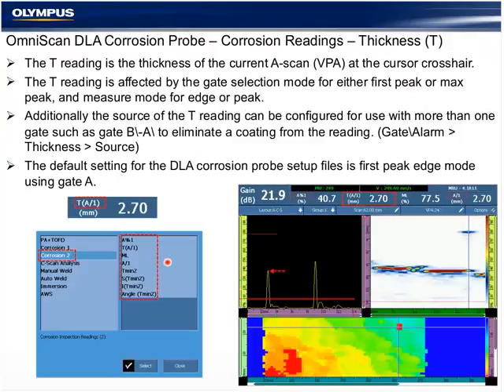In the three pre-configured files, they're also pre-configured using Corrosion Group 2 of the default OmniScan readings database. This gives us 4 readings in 2 groups, 8 total readings, typically what's necessary for a corrosion inspection. On any single point, we'll see the T reading, the material loss, and the amplitude.